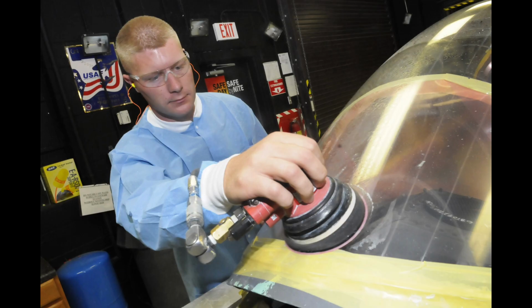Meanwhile, regulatory frameworks struggled to keep pace. Certification authorities rewrote standards, often reactively, in response to discovered weaknesses. Requirements for full-scale fatigue testing of cockpit sections became mandatory. Accelerated aging tests simulated ultraviolet exposure, humidity, and temperature cycling. What had once been optional became non-negotiable. Aircraft manufacturers absorbed the cost reluctantly, but the data was irrefutable. Designs that survived extended testing proved dramatically more durable in service. Incident rates declined. Confidence, this time grounded in evidence, slowly returned.